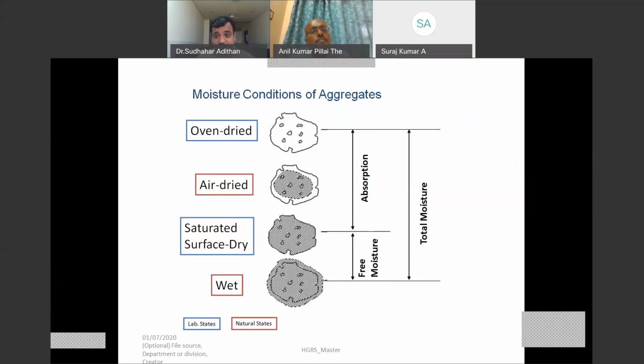The moisture content of the aggregate, the behavior of the aggregate vis-a-vis moisture, matters, because all our mix designs are done based on the saturated surface dry condition. So while choosing alternate aggregates, we should have a cognizance of whether our aggregate will be able to achieve this condition during the mix. If not, what will be the condition of the aggregates when we use it practically, and therefore what should be the kind of alterations you should do to the mix design itself.